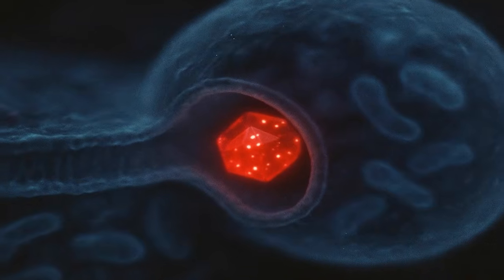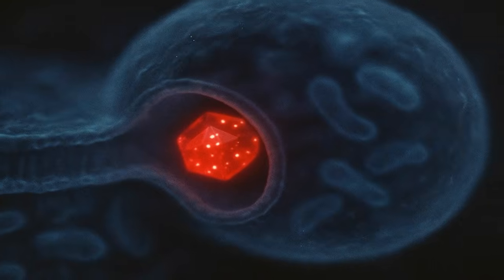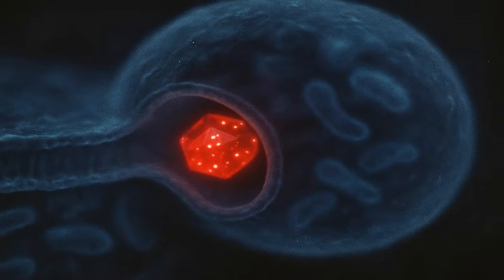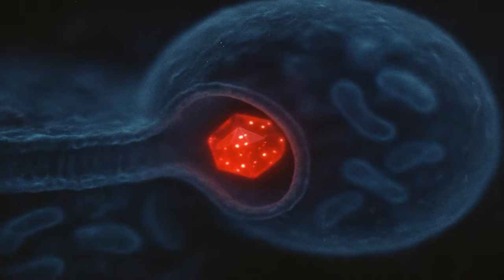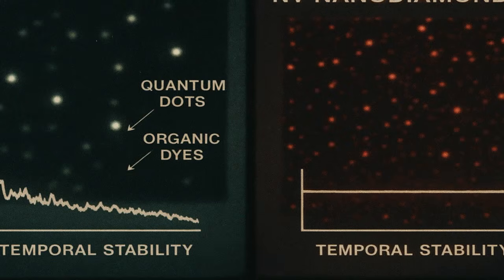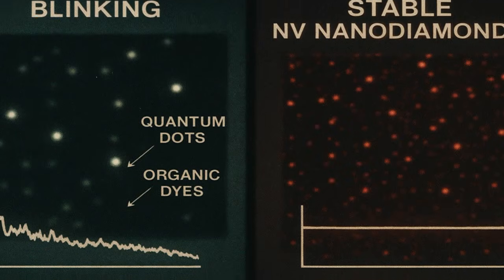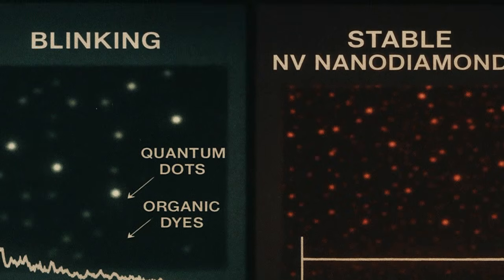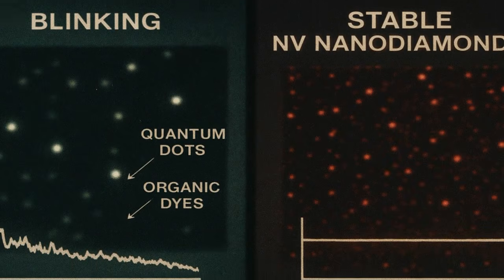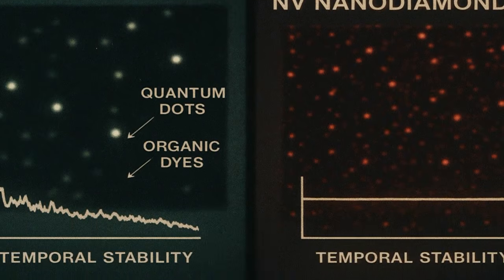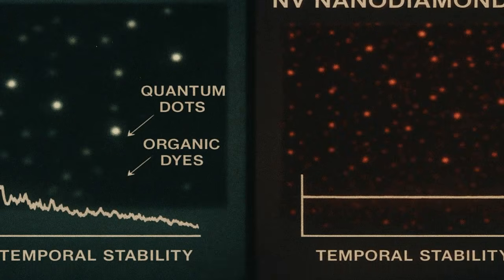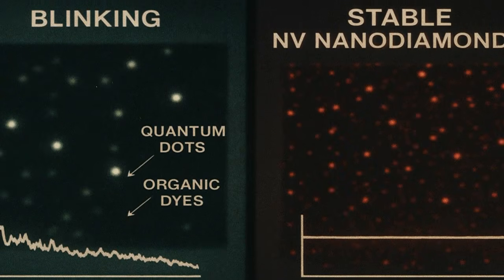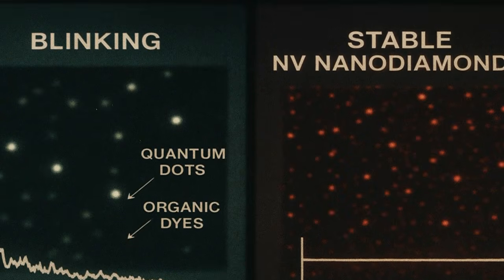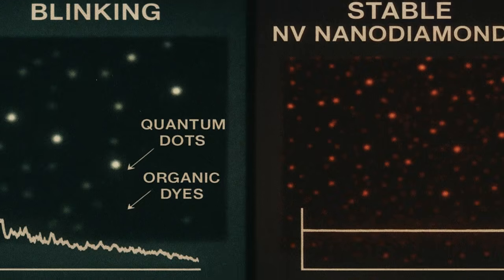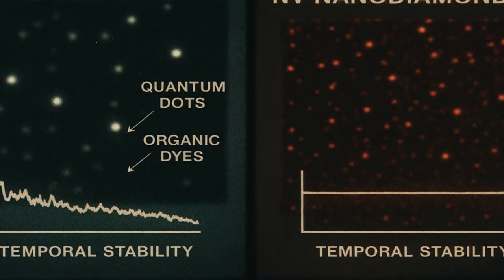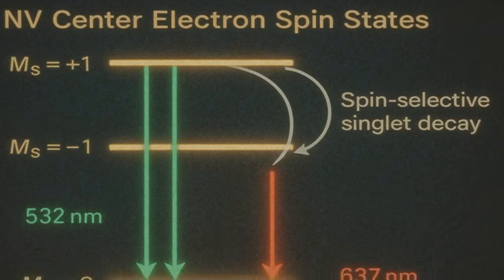Sounds impressive until you calculate per atom. The sun contains 1.2 times 10 to the 57 hydrogen atoms. Divide luminosity by atom count. You get 3 times 10 to the negative 31 watts per atom. An NV center at saturation with a 13 nanosecond radiative lifetime emits about 4 times 10 to the negative 19 joules per photon at 637 nanometers. At 300,000 photons per second, that's 1.2 times 10 to the negative 13 watts per atom. The diamond wins by 18 orders of magnitude.